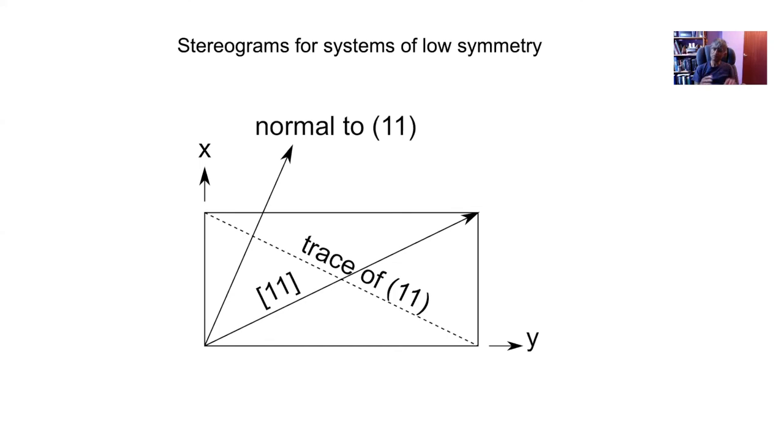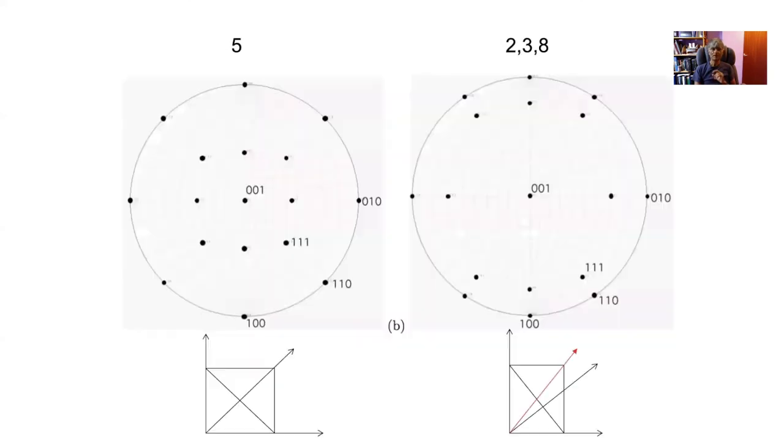So you cannot actually use the method that we used for dot products in one of the lectures where we were finding angles. There are other techniques to do that. But you need to be careful that directions and plane normals with the same indices are not necessarily parallel. Obviously, if you're looking at this 100 direction and this is the 100 plane, then the 100 direction happens to be parallel to the normal to the plane with the same indices. But that's a special case. All other planes and directions will be oriented differently in space, even if they have the same indices. Now, in the case of the cubic stereogram, which I've illustrated here,